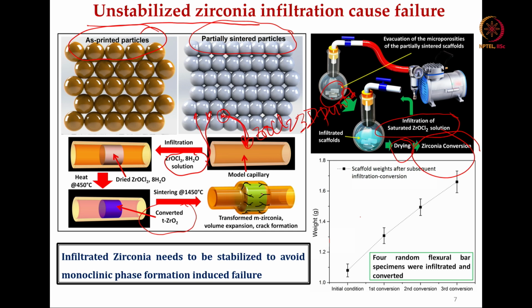And then if you sinter, many times we see that it can transform to monoclinic zirconia, with volume expansion and crack formation. So, infiltrated zirconia needs to be stabilized to avoid any monoclinic zirconia phase transformation. That is what we learned when we strategized this particular zirconia infiltration.